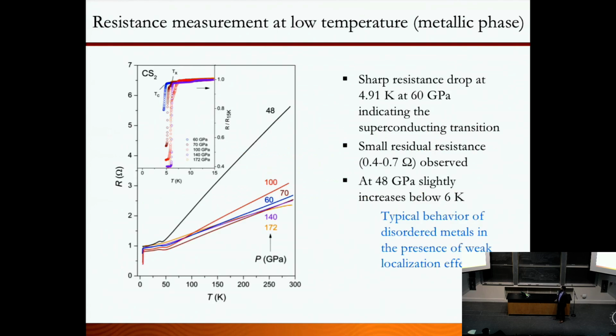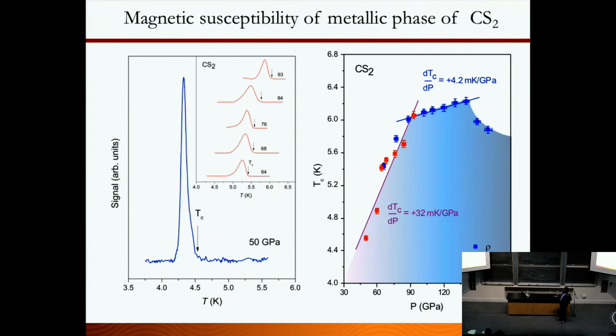So just to test that, we did the conductivity measurement at low temperatures, and we see a clear indication of a drop in resistance, a superconducting phase transition. The highest TC was 6.02 Kelvin. So it's not as high as room temperature, but it's high enough for this kind of material to have interesting phenomena. And the magnetic susceptibility confirmed that. This graph shows TC coming from the magnetic susceptibility and the resistance. Red are the magnetic susceptibility, and the blue ones are the resistance. So from both you can confirm that it's superconducting, from the magnetic measurement and the conductivity measurement.